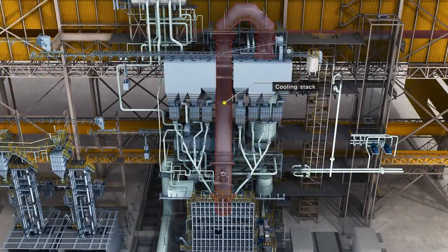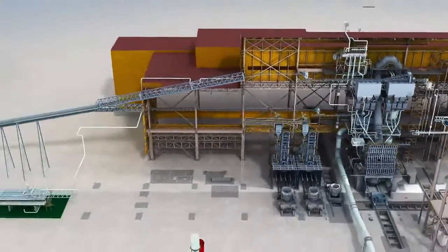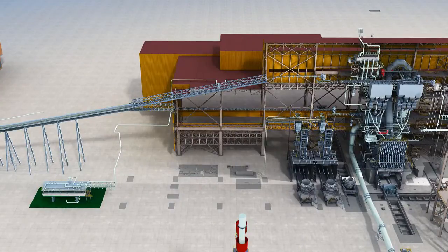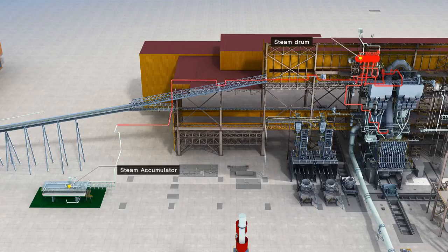The cooling stack over the hood, located at the top of the skirt, received a lot of radiation heat and consists of membrane tube for cooling. The off-gas temperature at the converter mouth during blowing is approximately 1,500 degrees Celsius, which is cooled down after passing through the hood and cooling stack. Radiation heat exerted on the cooling stack will generate steam through the boiler system. The generated steam is stored in the steam drum and steam accumulator, which is installed outside.